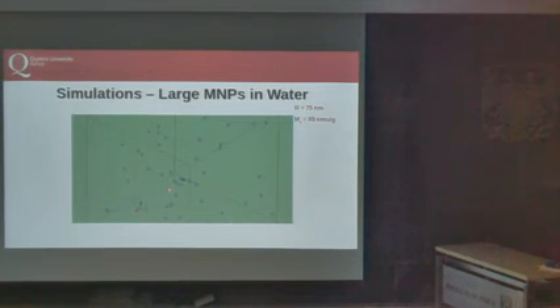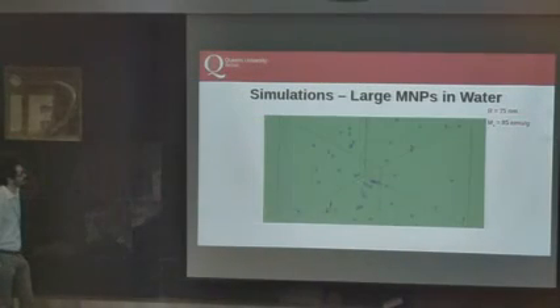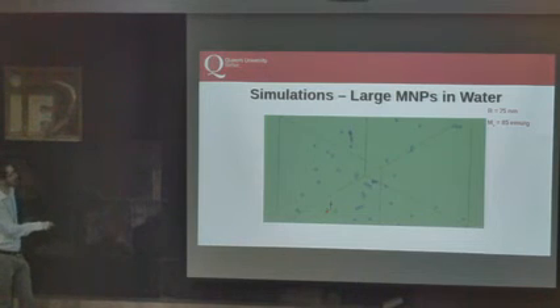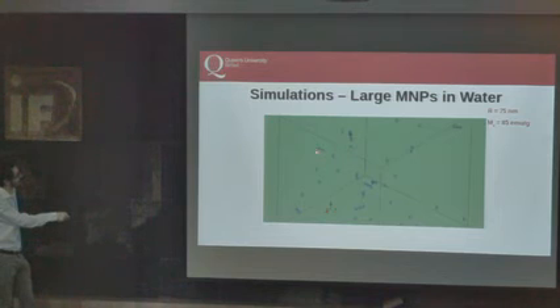And you can see they clearly tend to form short chains. Here there was an event, perhaps. So we use periodic boundary conditions. So if you see some magnetic nanoparticle disappearing, it will appear on the other side of the box. And okay, here we have a longer chain. Here there was an event.